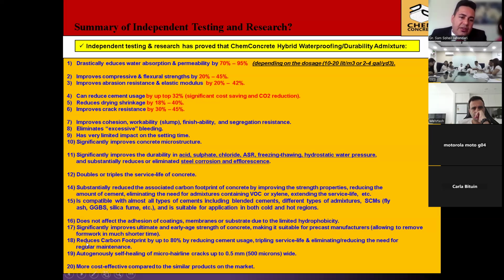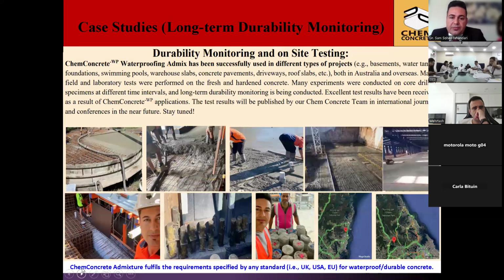It reduces carbon footprint by up to 80% by reducing cement usage, tripling service life, and eliminating or reducing the need for regular maintenance. It has autogenous, self-healing capability to heal micro cracks up to 0.5 millimeter, even a little bit better than crystalline admixtures. And also, it's usually the most cost effective compared to other similar products on the market.